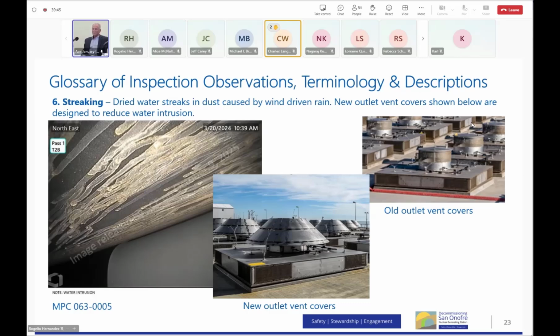And that is right. So on the left, just look at that water intrusion. That all came in during a rainstorm. It ran down the side of the canister, and it dried up quickly because the canister's hot. The canister's got fuel in it, and the surface temperature's warm, and it evaporates the water. And within hours, it's dry as King Tut's tomb again, right? So it's really not a problem, but it isn't very pretty. And we didn't like the idea of that happening for however many years these canisters have to be here.